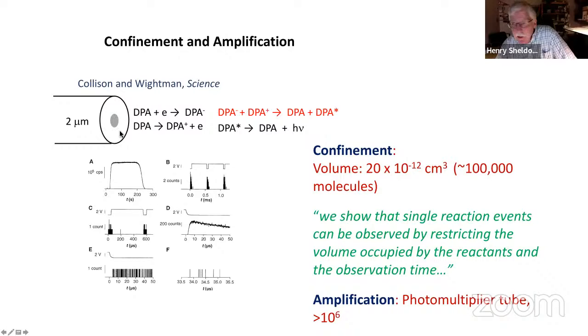All right. The Collison and Wightman experiment, okay, well, this is a microelectrode in bulk solution. So at first glance, it's not obvious what the confinement is, but the confinement is that the molecules, the reactive molecules, are constrained close to the surface in the diffusion layer. All right, so if this is a 2-micron electrode, all these molecules being generated are within 10 microns of the surface. That's a volume of about 10 to the minus 12 cubic centimeters. They still got a lot of molecules there. There's 100,000 molecules in this experiment in the diffusion layer. All right, that's too many to make observations of single events.